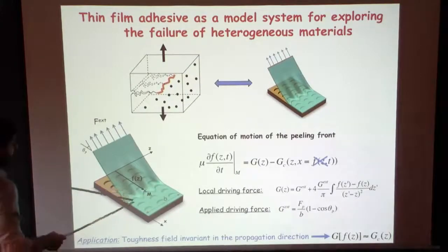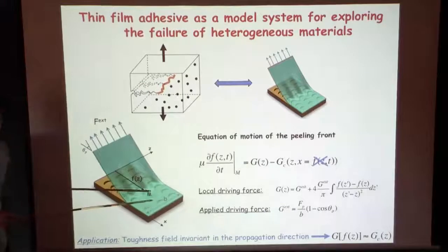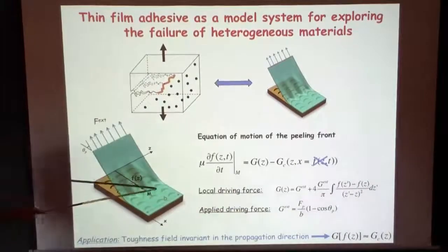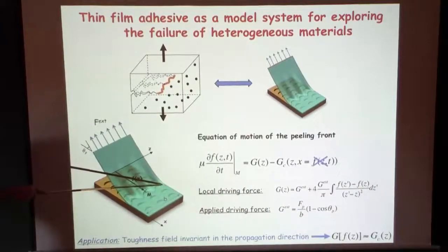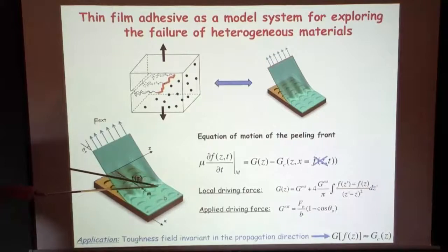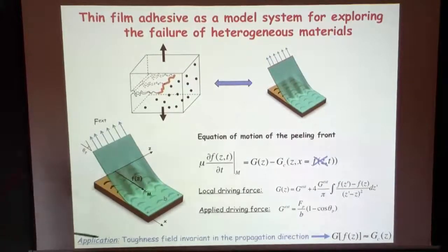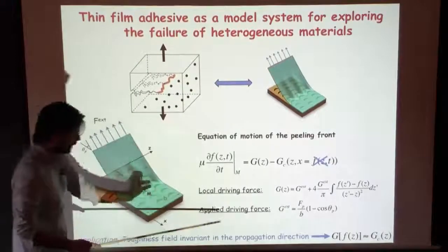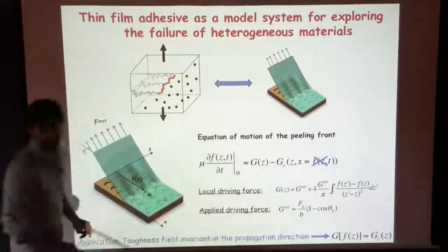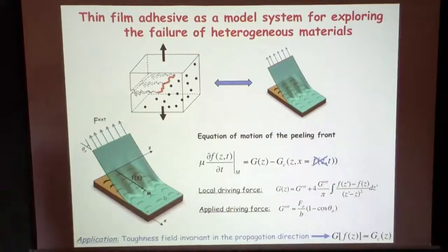Because you talk about pseudo-line elasticity, you don't have so much choice. Behind this non-local term, you have an argument of de Gennes that tells you that if you modify your interface over some length scale lambda, you have an influence in the bulk over the same length scale, and you will always end up with this kind of non-local kernel. So the only difference we can have is the prefactor.